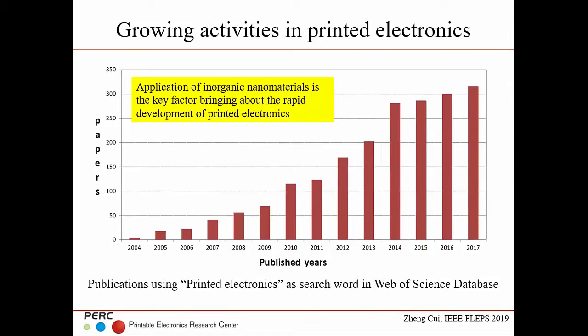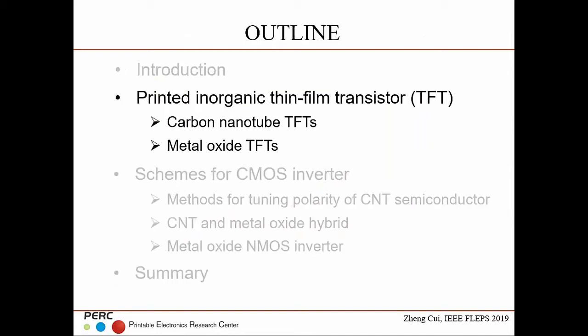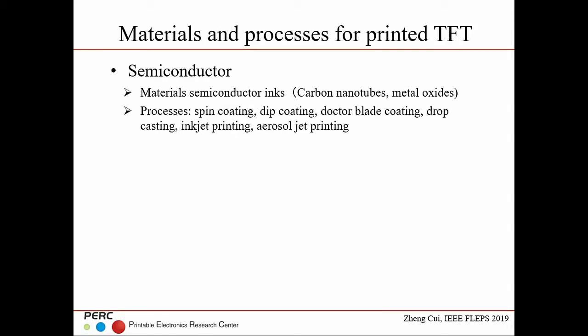So let's look at the work we have done. First, I'm going to introduce the work we did on the thin film transistor. As I mentioned, it's mainly the carbon nanotube and the metal oxide. For the thin film transistor, on the semiconductor side, we focus on these two materials, and we use spin coating, dip coating, doctor blade coating, drop casting, inkjet printing, and aerosol jet printing. We use all sorts of solution technology.